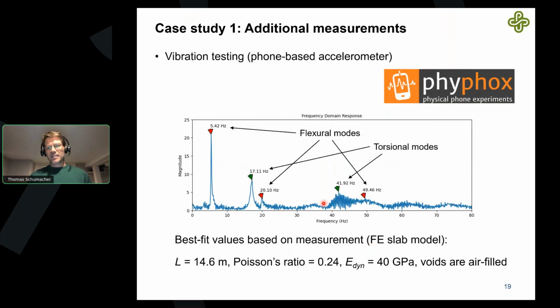Here's just some results from the vibration testing. I used a simple cell phone based measurement here. That's Phyphox, an app that you can use to measure the vibrations, the acceleration response. We just jumped on the bridge, measured the response. We identified some modes, some flexural modes of the bridge, some torsional modes. We did build a finite element model, a slab model, and basically played with the material properties, and we also tried to fill the voids with water and fill the voids with air. And the best results we got to match these peaks in the model were these, and the model told us the voids are most likely air filled.